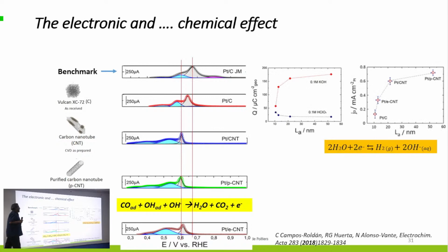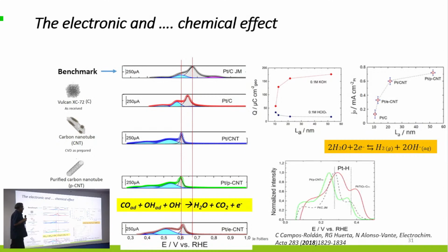So to make things a little bit short, we can calculate the charge here in two media, either in acid or in alkaline. You see in the alkaline, we have an increase of the charge, all right? And that goes almost in parallel with the exchange current density of the system. So we can say how this effect could be illustrated when you do the hydrogen underpotential deposition. There is this shift. The bond between platinum and hydrogen changes because there is a shift there.